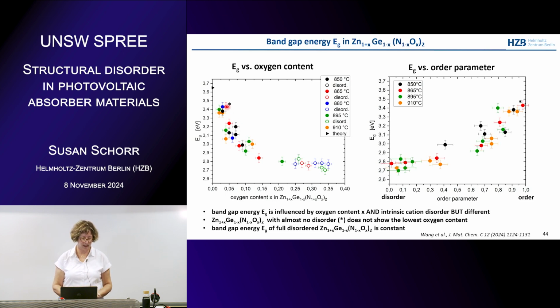If you look for this sample I marked with the star, this is the sample with almost no disorder. Here, almost, so this is the lowest disorder we have, but it's not the lowest oxygen content we have. And if we have fully disordered material, like here, then the band gap doesn't change anymore so much. In principle, then it's constant. Also, the open circles are disordered zinc germanium nitride, and then you see that the oxygen content changes, but not the band gap anymore.